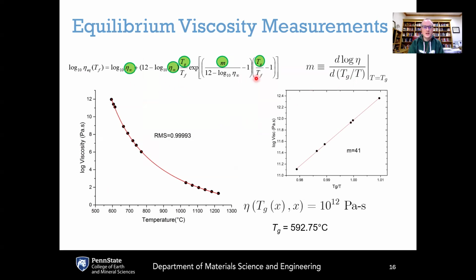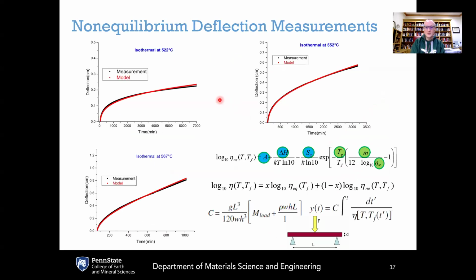What's shown up here is the MYEGA equation written in terms of Angell's parameters: the glass transition temperature Tg, the fragility index m, and the extrapolated infinite temperature viscosity eta infinity. My colleague Oscar made really careful measurements to get the glass transition temperature for Westminster Abbey glass, which he found to be 592.75 degrees Celsius, and the fragility index, which is 41. So we've got the key parameters here that we need for the equilibrium liquid viscosity.